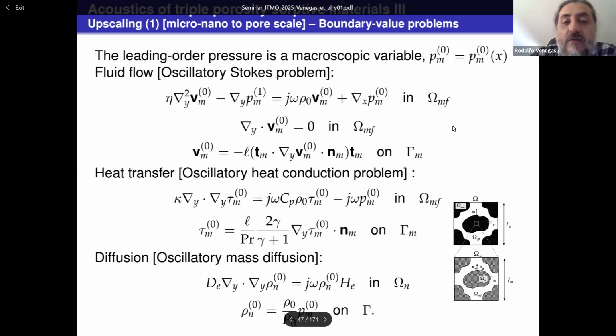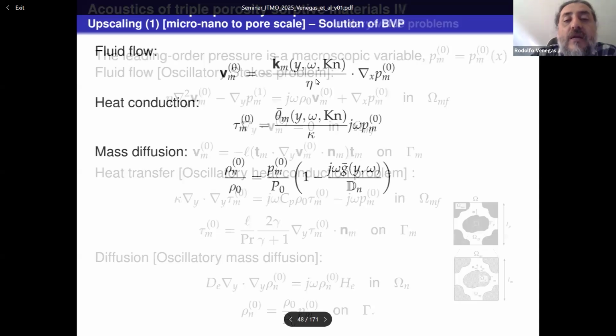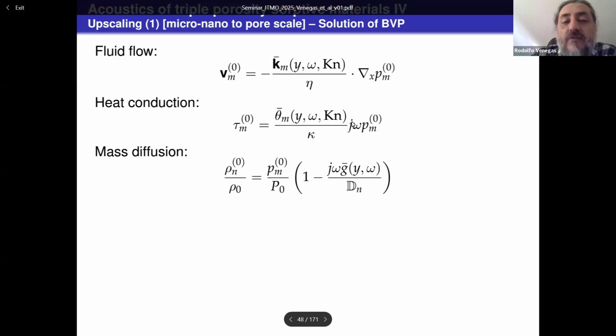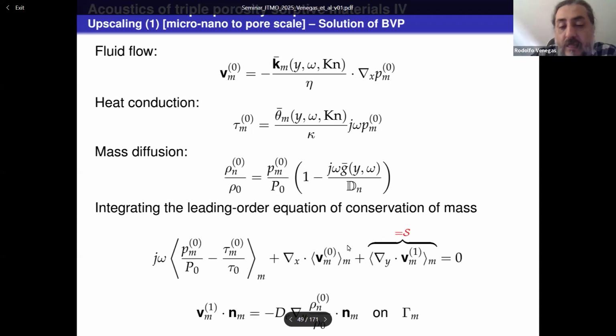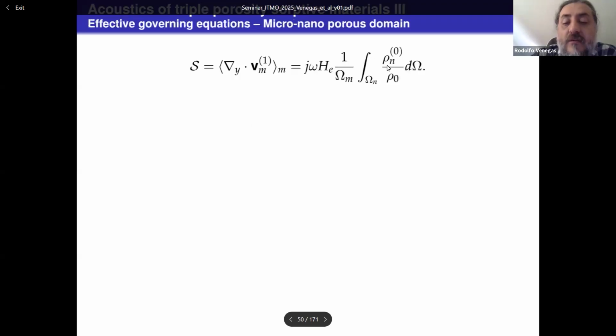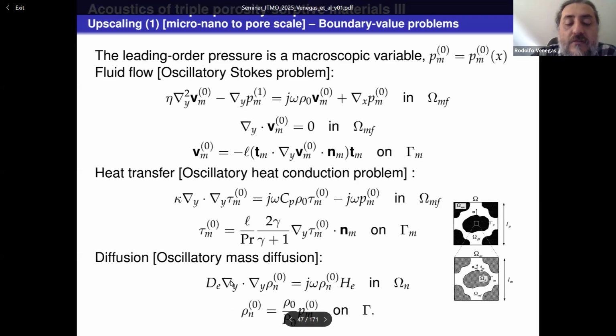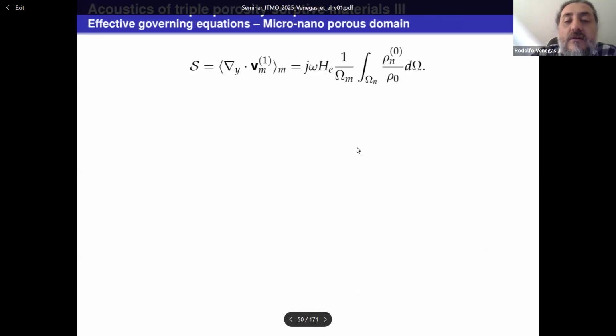So of these three problems, one of them is forced by the macroscopic pressure gradient, this one is forced by this, and this one is forced by this constant density here. So we can write the solutions in terms of operators acting on these forcing terms in this way. And after that, we work out the macroscopic description from the equation of conservation of mass, where in this case the source S is no longer zero as in the previous case, but rather is related to the mass flux. And this term here, if we apply the divergence theorem, we can use this equation, we get the Laplacian of this, and then we relate that to this term here to get this expression here.